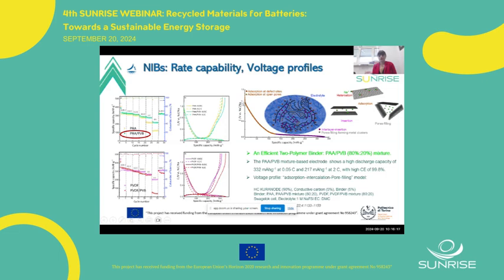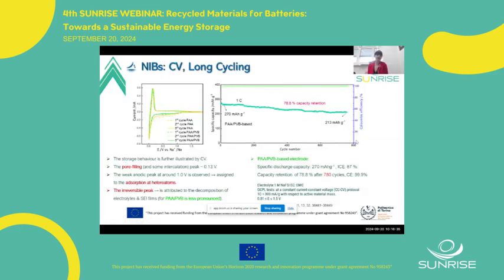The voltage profile of all the electrodes is shown, and we can see that in the sloping region we have adsorption, while in the plateau we have interlayer insertion and pore filling process for all the electrodes. The cyclic voltammetry for PAA and the mixture of PAA-PVB is shown, which is in good agreement with the voltage profile shown in the previous slide.